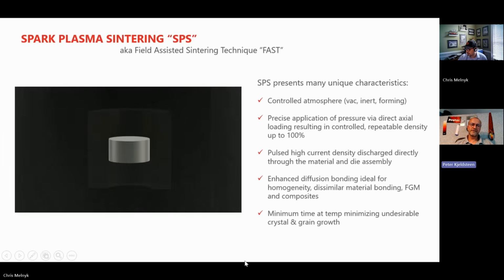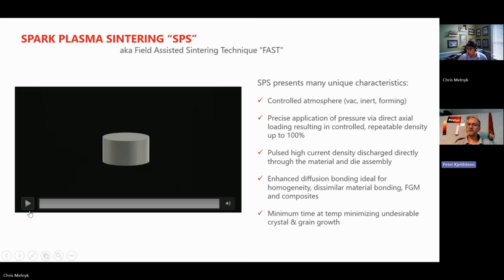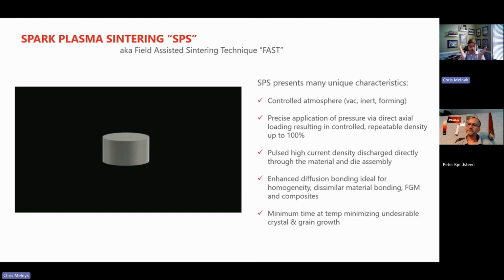So what is the pressure? Are we talking several tons per square centimeter? And that's another thing that you'll find differences. So that's heavily dictated by the material needs and also the tooling. You'll see some research papers on more niche applications where they have carbide tooling or silicon carbide tooling that has wedge shapes that are really concentrating, and then multi-wall dies that can take much more pressure. And those will get into the gigapascals of pressure. But that's really the exception. The vast majority is sitting in the 20 to 50, maybe 80 MPa pressure ranges.